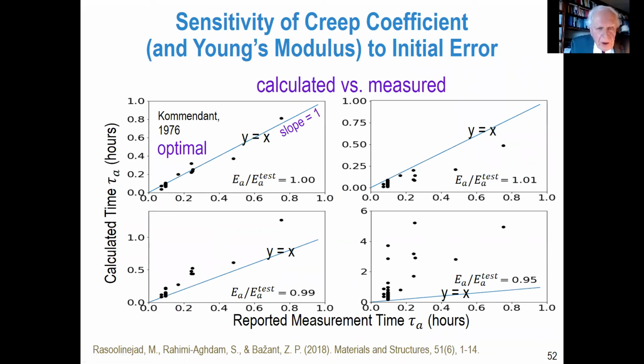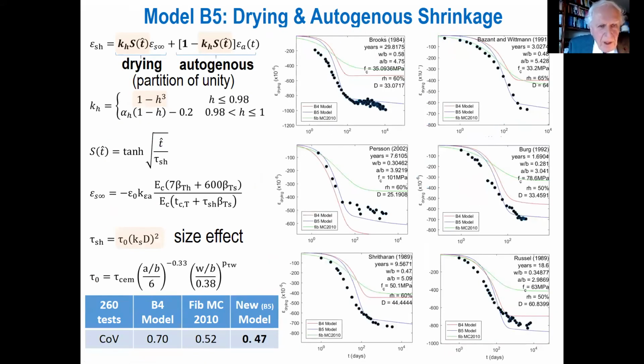One can also check how it works by comparing calculated versus measured values. If you don't make the correction, the measured values for the initial data do not work well, as you see here in these plots. But after optimization, measured versus calculated goes as slope 1 and 1 here, where it must be if the fit is good. And this is for famous data from Berkeley, which are probably the most accurate of all, by Kommendant and Polivka, my fellow countryman.